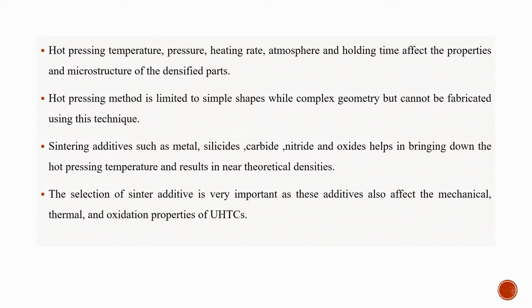Sintering additives such as metal, silicides, carbide, nitride, and oxides help in bringing down the hot pressing temperature and result in near theoretical densities. The selection of sinter additive is very important as these additives also affect the mechanical, thermal, and oxidation properties of UHTCs.